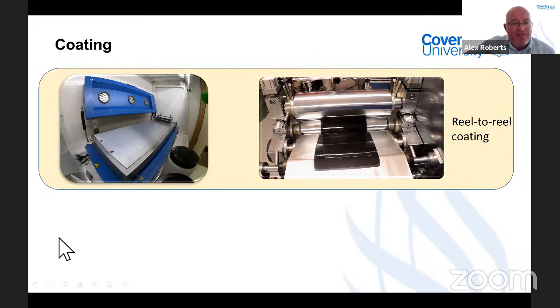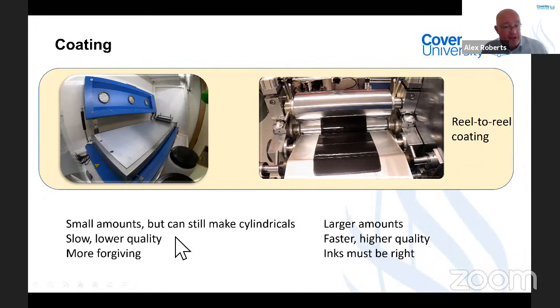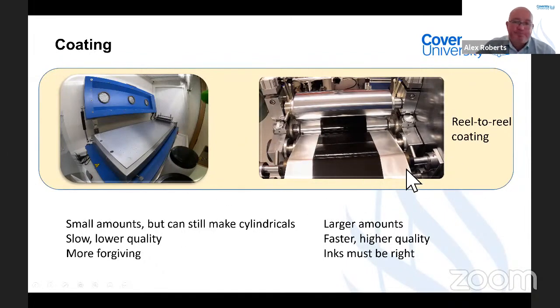And this is really, really effective for small amounts of electrodes. And you can get longer drawdown tables so you can still make larger electrodes. And it's very, very forgiving with your ink and can give a reasonable number of consistency. What you can see on the right-hand side is the reel-to-reel coating. So this is on my small reverse comma bar coater. And this is typically used for larger amounts of ink. It's faster, it can give higher quality electrodes, but your ink must be just right.